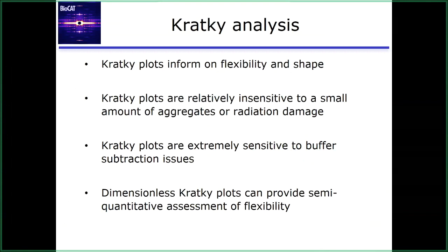To summarize Kratky analysis, the plots inform on flexibility and shape. They're relatively insensitive, well, let me clarify that. In some ways, Kratky plots are relatively insensitive to a small amount of aggregates or radiation damage, because we're multiplying by Q squared, all the stuff at low Q gets squished down and you can't see it.